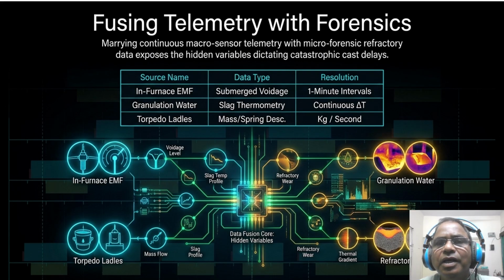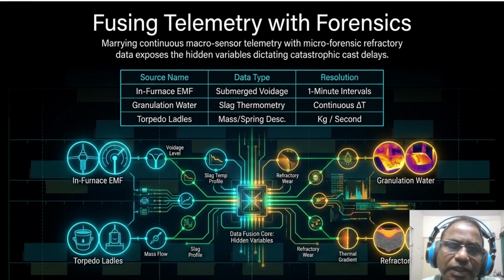The operational impact is significant. If your torpedo ladle mass flow starts dropping while slag temperature remains high, you have got a localized hearth blockage. So if you wait for the level probe to tell you, you are already behind the curve. Use this fused data to predict the delay before the cast flow even reports it. This is fantastic. One of the most critical variables we track through this fusion is the impact of gap time on your protective layers.